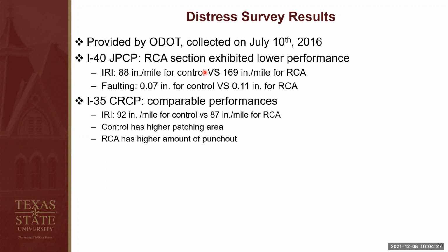The RCA section had a higher international roughness index. It also had higher faulting value compared to the control. For the CRCP, however, the performance was very comparable between the RCA and the control. The international roughness index was very similar between the control and the RCA. Control had a higher patching area, but RCA has higher amount of punch out.